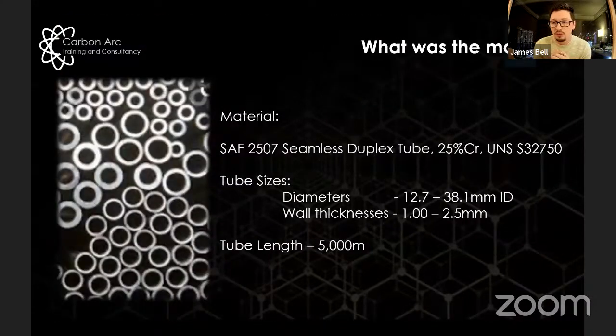The material was all super duplex UNS 32750 tube, again, produced directly for the project to order, mainly from Sandvik in Kromeriz in the Czech Republic. And they're all small bore tubes. So they ranged from 12.7 mm to 1.5 inch, 38 mm ID, with a wall thickness between 1 to 2.5 millimeters. So these are very small tubes.